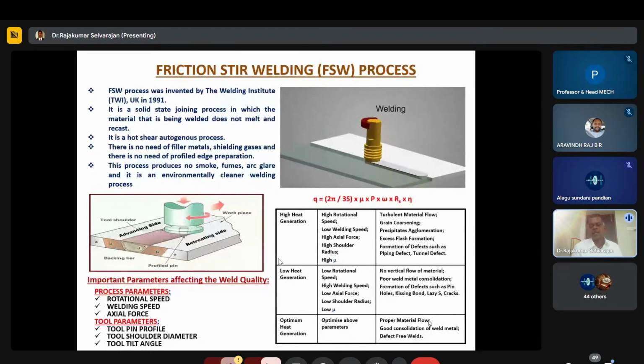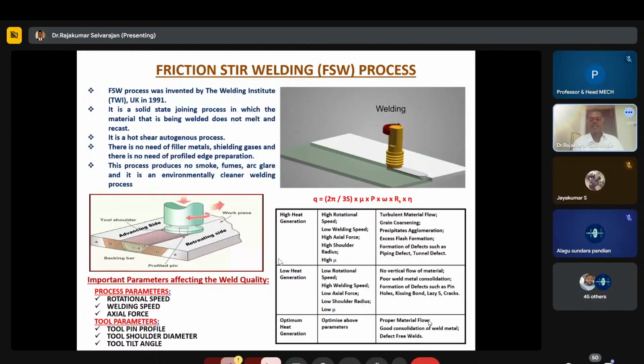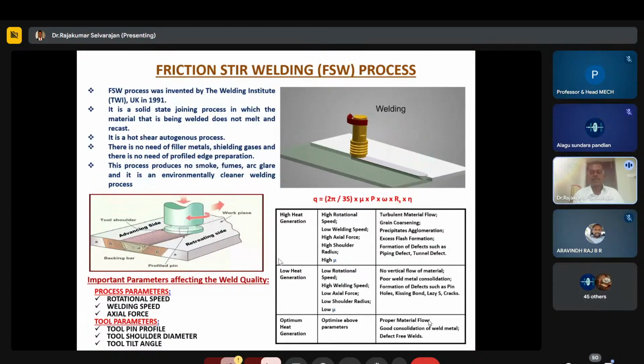If the heat input is higher, the turbulence of the metal flow will be high, and in the metallurgical aspect, grain coarsening, precipitation and agglomeration will take place. Because of the high heat generation, excess flash formation will happen, and defects such as piping defects, tunnel defects and kissing bonds can form when increasing the heat input.